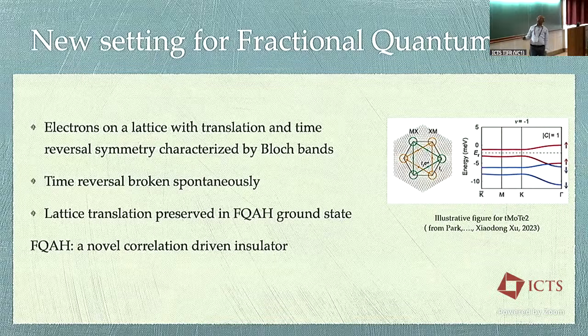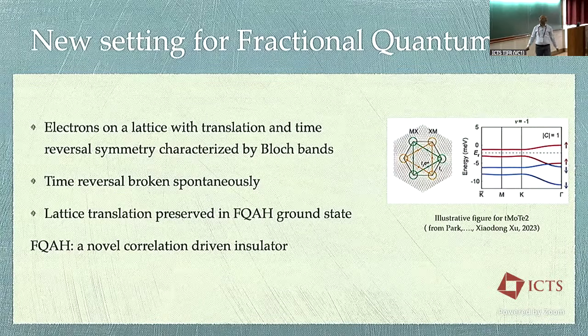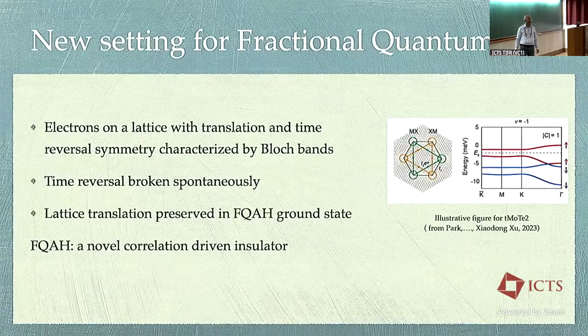You have electrons on a lattice with lattice translation symmetry and time reversal symmetry, and microscopically, the electrons have Bloch bands. So this is a picture of the band structure calculated in the experimental paper, in Xiaodong Xu's paper. This is the electronic band structure. And time reversal is broken spontaneously. We don't know this from experiments, but from all the numerics that people have done, we know that lattice translation is preserved in the observed fractional quantum Hall ground states. We don't have a direct experimental proof, but we have pretty good numerical evidence that lattice translation is preserved.